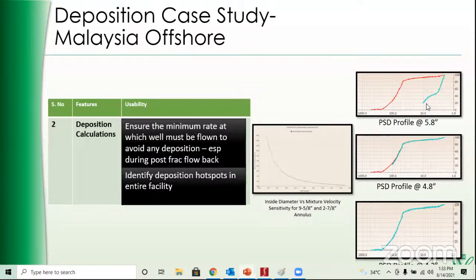But with time, very few particles were getting transported, because as the sand deposition was taking place in the annulus, the effective hydraulic diameter was decreasing. There was a case where the effective hydraulic diameter came to only 4.2 inches, and all the sand particle sizes were able to get transported to the surface. So this is also a type of analysis.